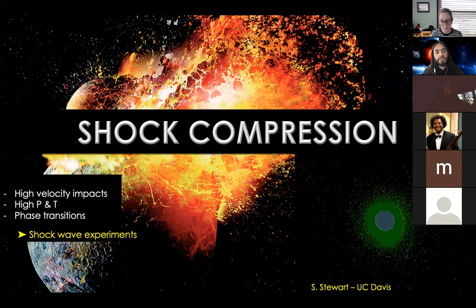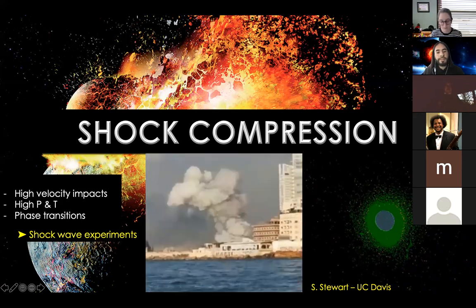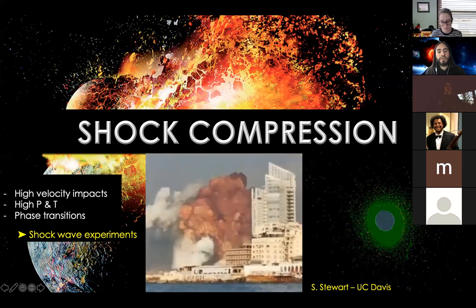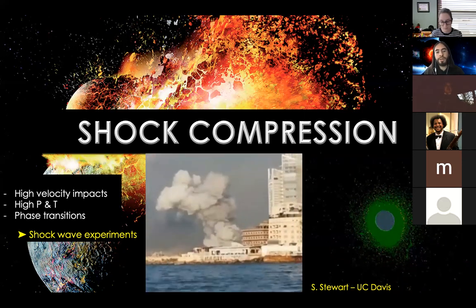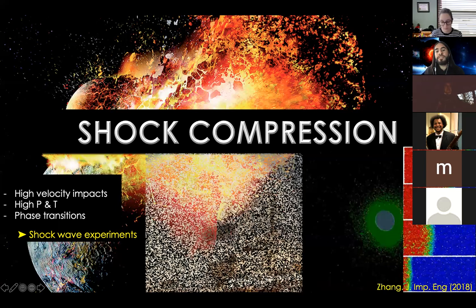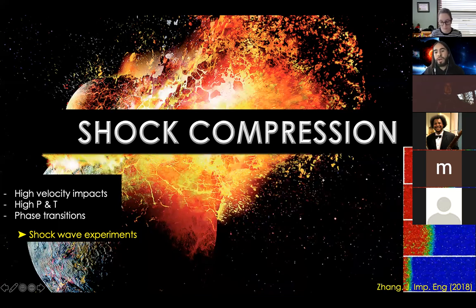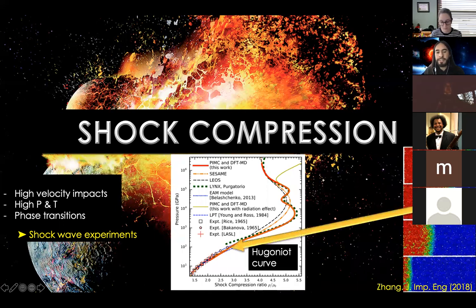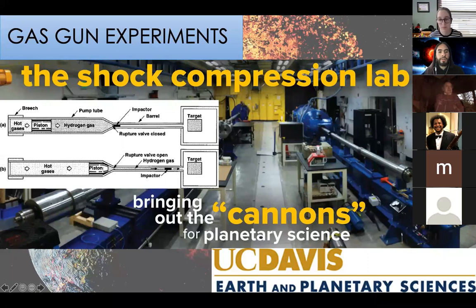So the idea is to generate these shock waves, these violent collisions in the lab. And if you remember the unfortunate events in Beirut last year, where you saw this factory exploding, it generated this blast. And this blast is basically a shock wave. And this shock wave generates new states of matter behind it, where matter is compressed at higher densities and higher pressures and also higher temperatures. So that's a way that we have to access these new states of matter. And the collection of all these new states of matter in shock events, we call them the Hugoniot curve of a material.